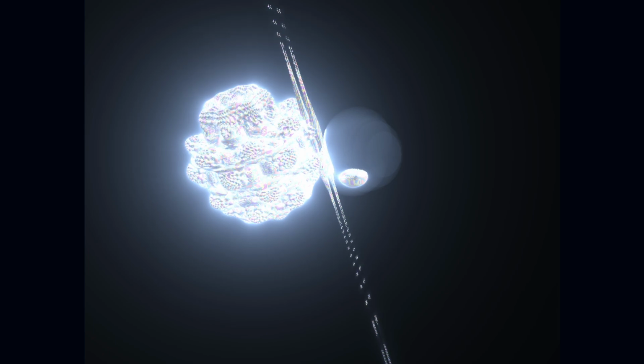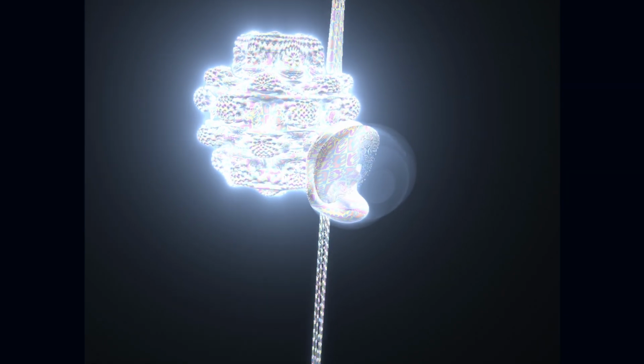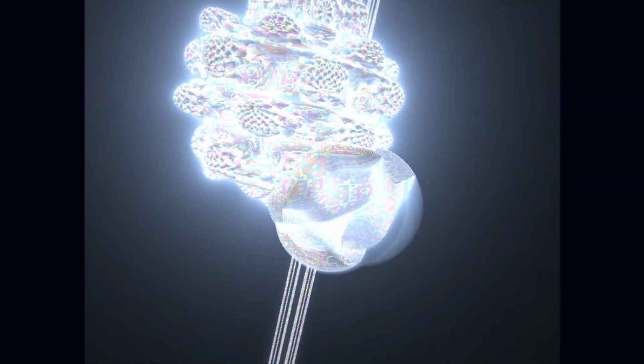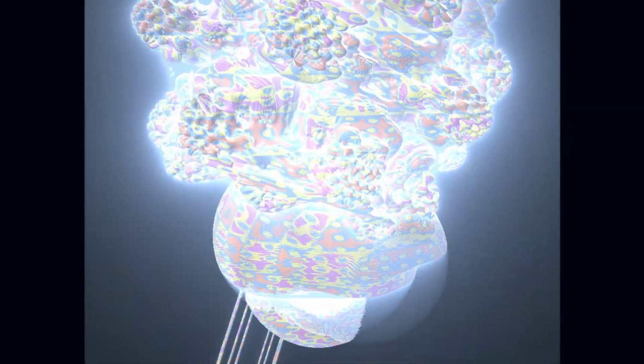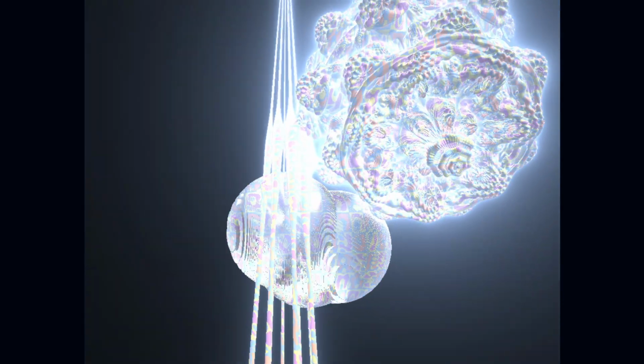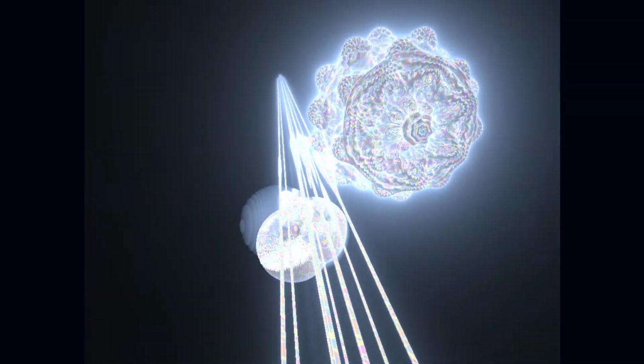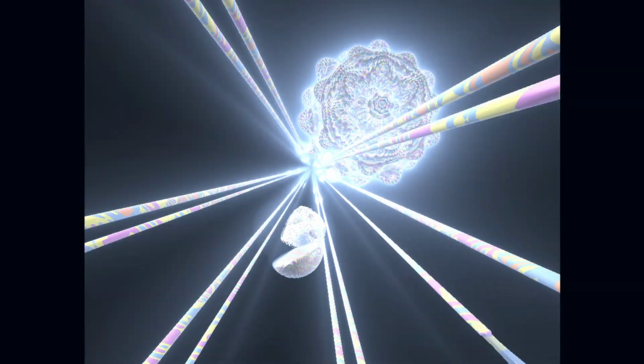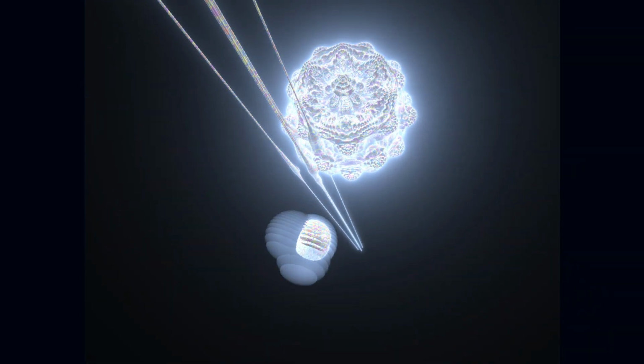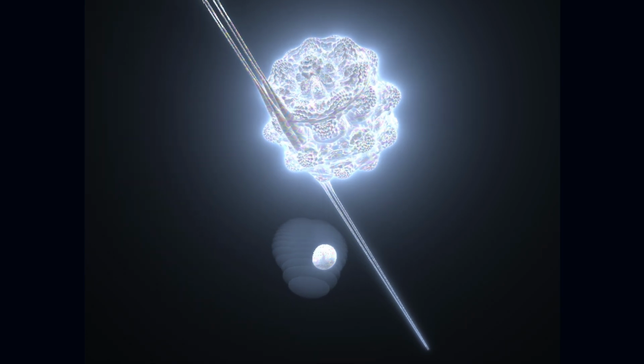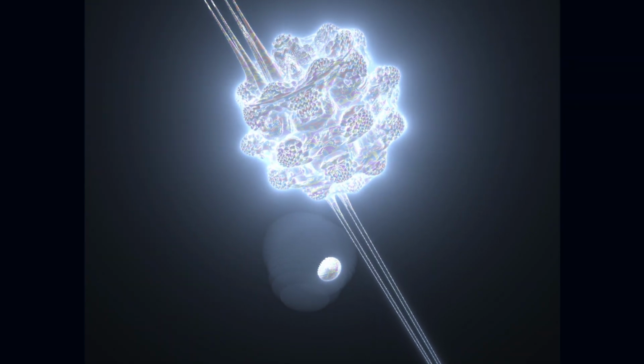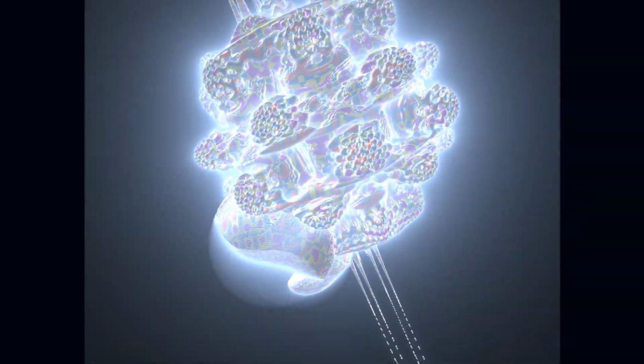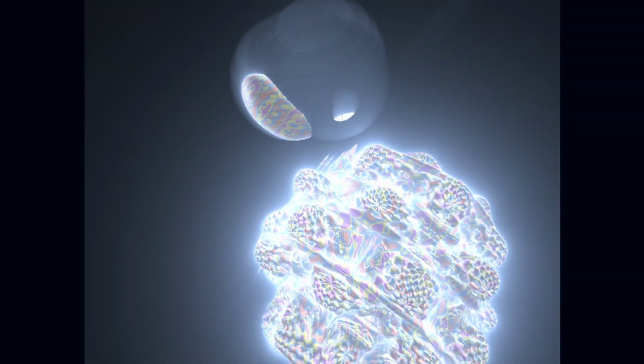Superconductivity. Exactly. And the strength of this electron-phonon coupling, the same alpha that determines our polaron mass enhancement, also dictates the binding energy of these Cooper pairs and, consequently, the superconducting transition temperature, Tc. It's an incredible balancing act in nature. Stronger coupling generally means heavier polarons, but also stronger pairing and higher Tc up to a point. Wow. Okay, this deep dive has really shown us that the influence of phonons on an electron's mass in a crystalline solid is, well, a cornerstone concept in condensed matter physics.